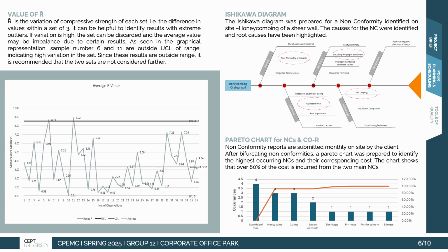R bar is the variation of compressive strength of each set, that is the difference of value within a set of 3. It can be helpful to identify results with extreme outliers. If the variation is high, then the set can be discarded as the average value will be skewed. As seen in the graphical representation, there are two samples, sample number 6 and 11, which are outside the upper control limit, which shows that within the set, there is a large variation in compressive strength. So it is recommended that the set isn't considered.